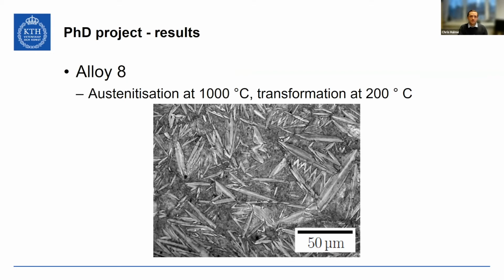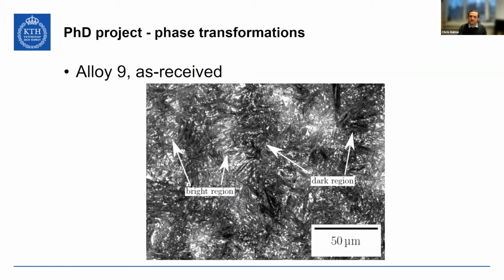If we look at the more extreme high nickel, high cobalt variant that I generated, we've got extensive banding, and I remember being in the lab with Steve, looking at this one day, and just with the naked eye, you could see the banding after you etched it in nital. It was beautiful. Doesn't come across so well on the micrographs, but I hope you can see alternating bright and dark bands running vertically here, and a bright band coming across. Within those bands, they look pretty similar, but they are very pretty when you see them with the naked eye and at low magnification. But in both cases, I still form bainite.